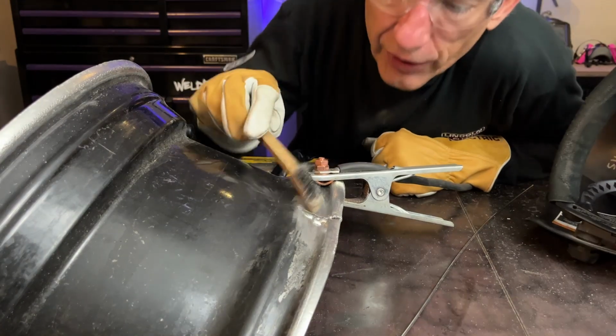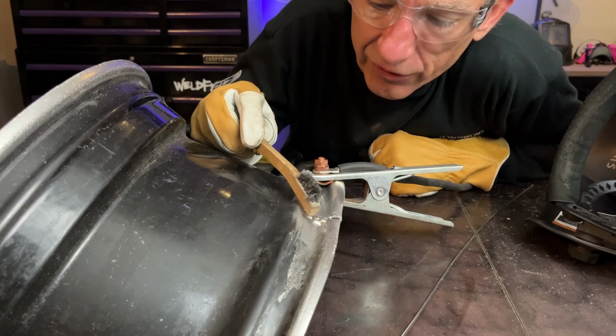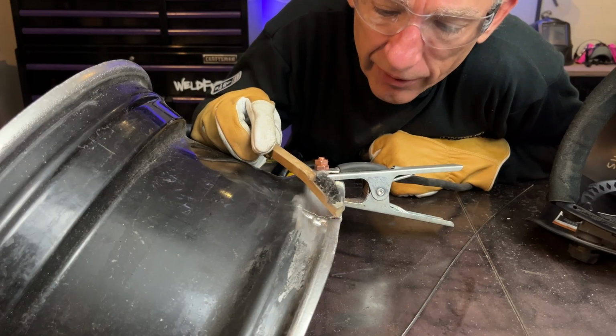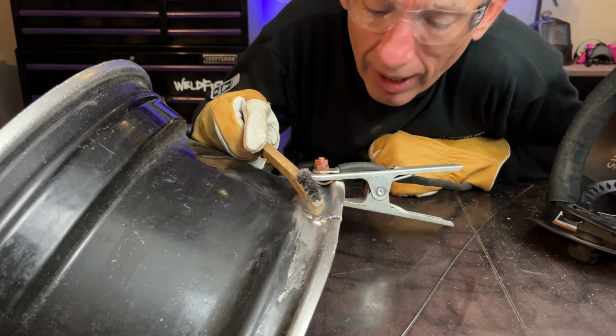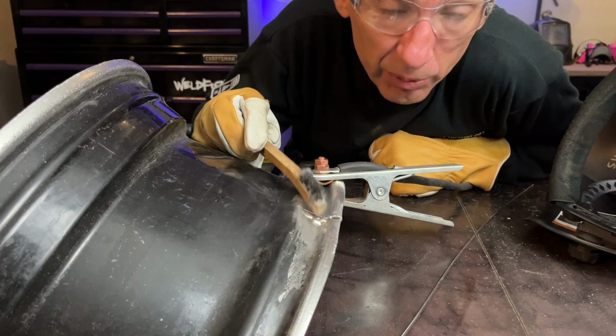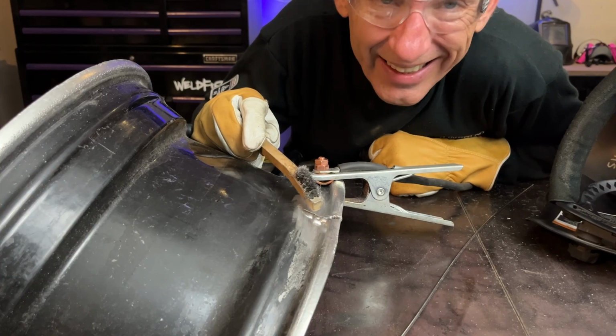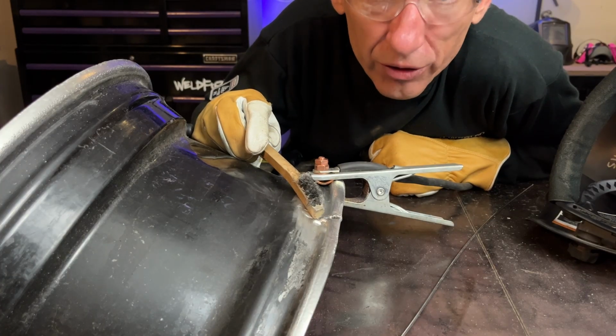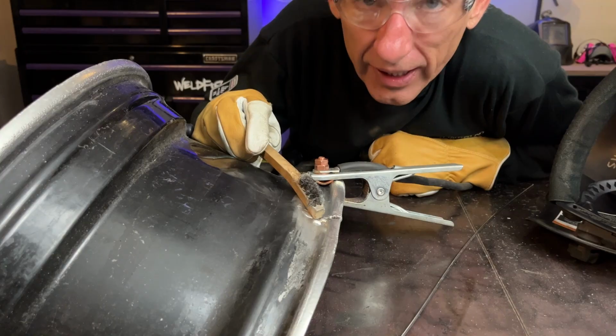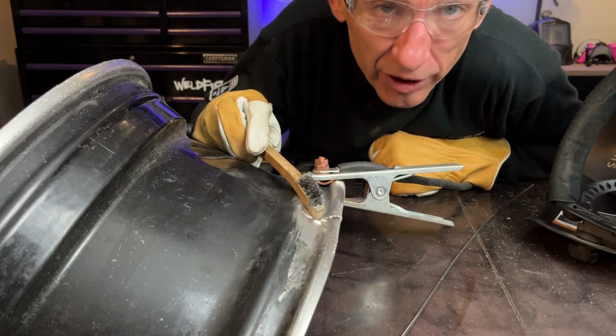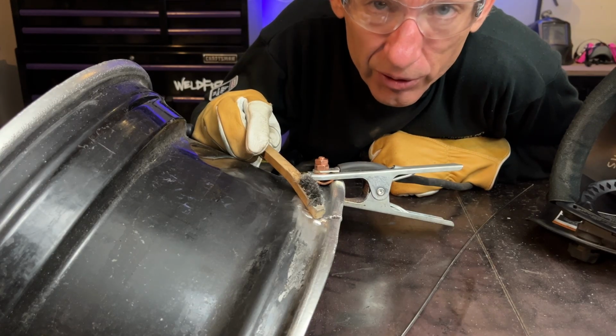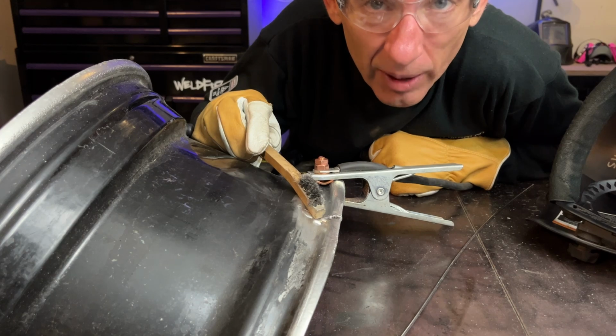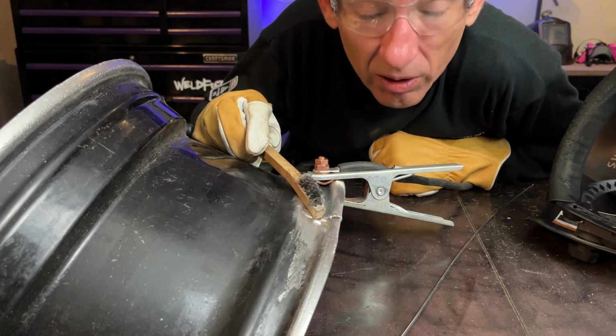Okay, we rolled this thing over into the flat position, and like I say, what I've got to do is clean this up, get it all welded up to the corner. Then I'm probably going to do a little bit of sanding and a little bit of touch-up cleanup, because cast aluminum is notoriously porous. So it's going to off-gas on you the more that you melt it. So what we have to do is take it one step at a time, right? Cross your fingers, hope and a prayer, never hurts.